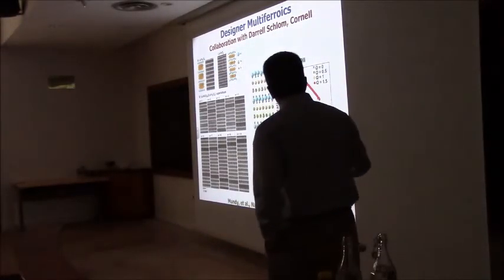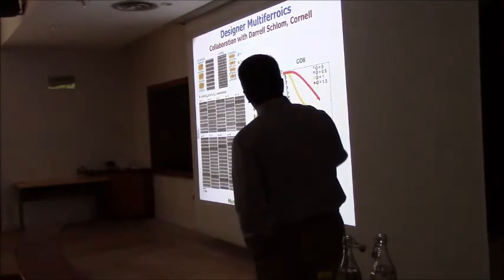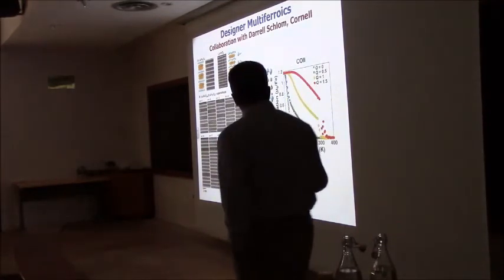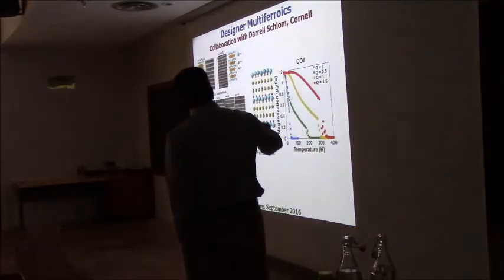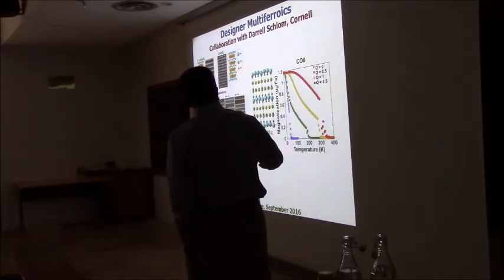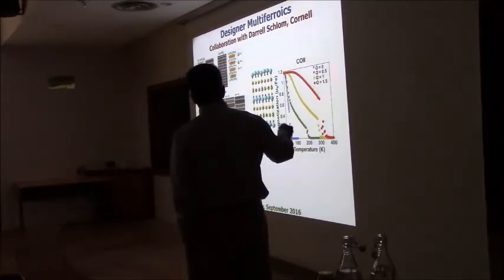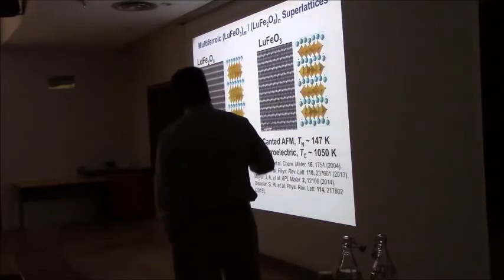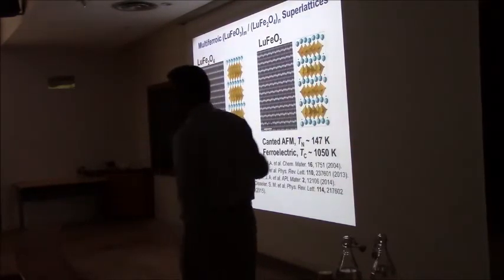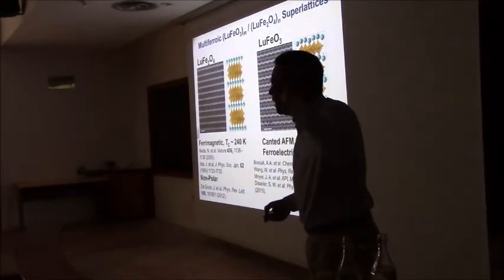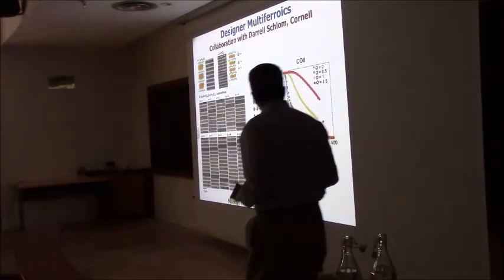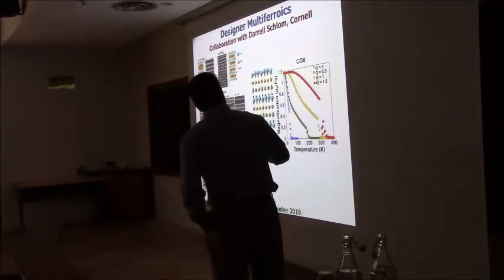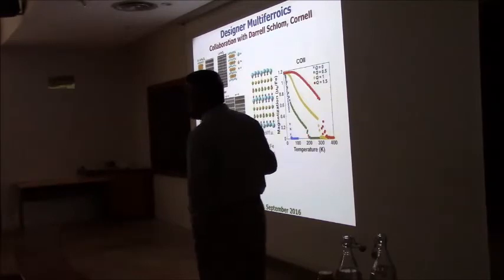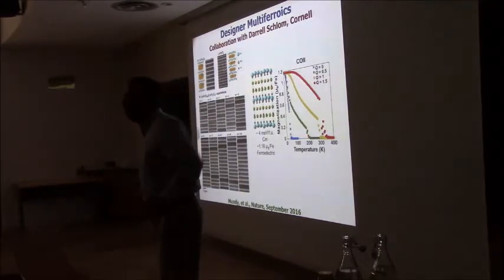What we see, and this is calculations from Craig Fennie, is that the magnetization per iron actually scales with this Q parameter. What is this Q parameter? The Q parameter is this distortion. I'm going to come back to it again. That's the kind of spontaneous distortion in the crystal. It seems to scale with that distortion, which says that there's some coupling through the lattice.